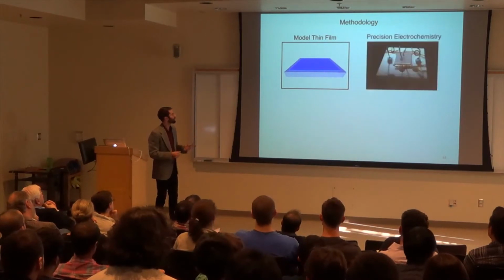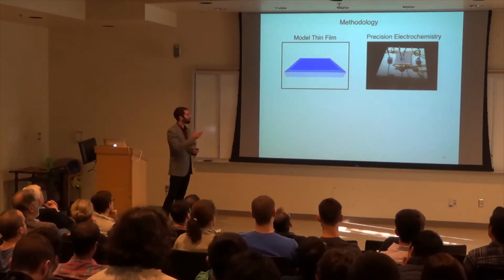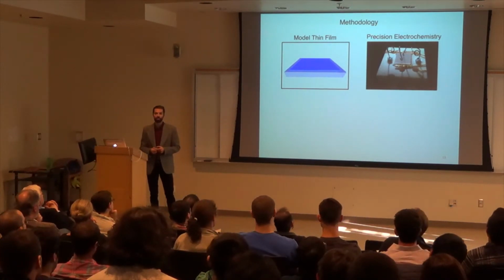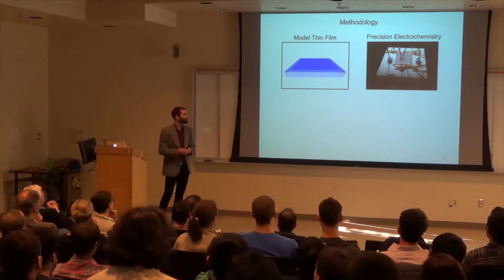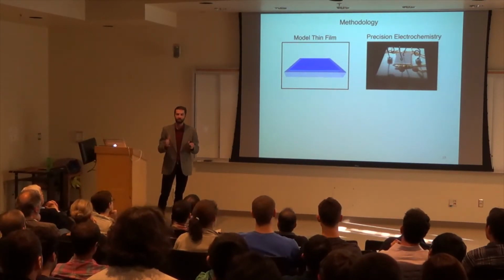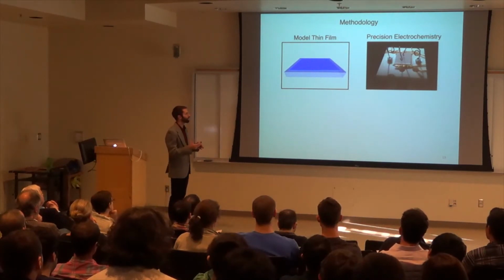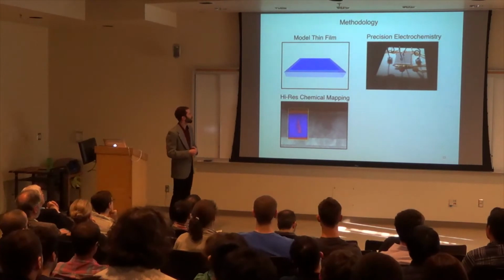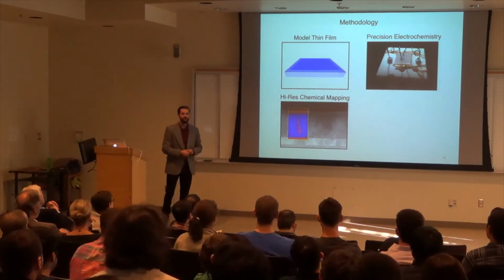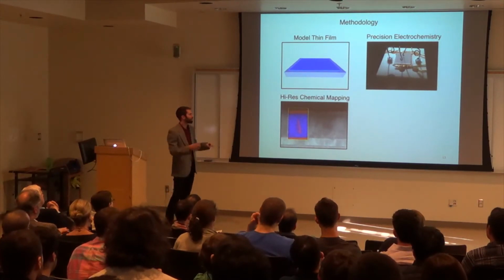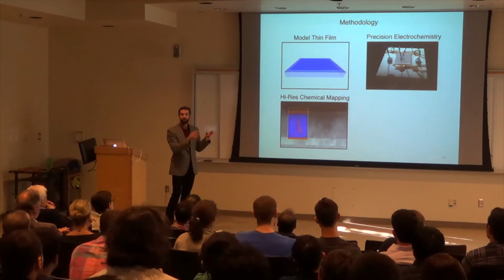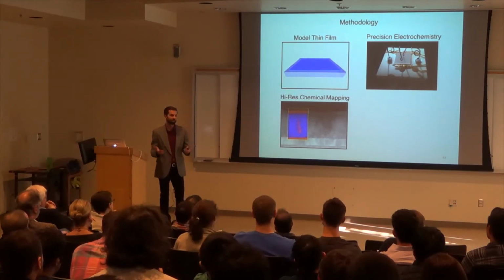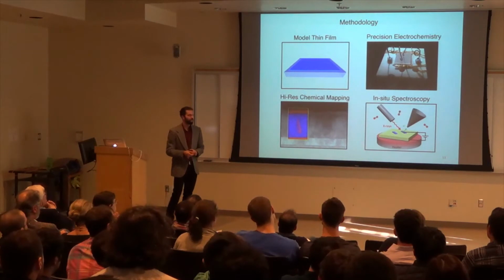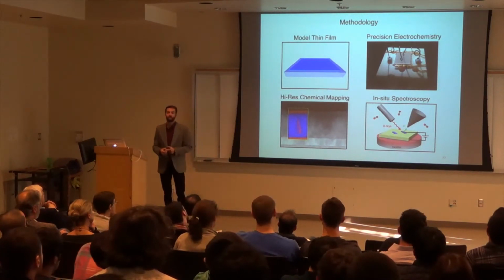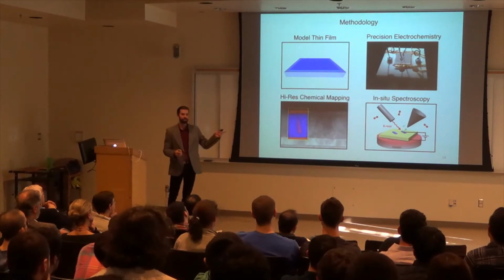And so once we study these systems and what we find on the surface, we then want to test them in a very precise electrochemical setup that we build ourselves. It's very clean, so that we can deconvolute any type of things that might try to confuse us in our results. Then, to analyze our thin films, we use things like high-resolution chemical mapping. And this allows us to zoom in and perceive what is found at the surface, both structurally and chemically speaking. So what is that at the top few nanometers of the surface? And then finally, these measurements are done ex situ. We're then going to try to see what the surfaces look like and compare them ex situ to what the surfaces look like under relevant operating conditions using synchrotron radiation and in situ spectroscopy.